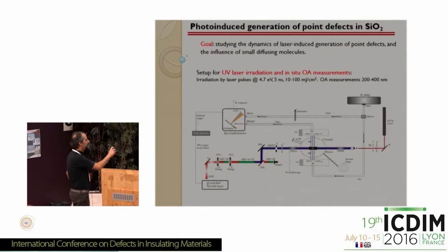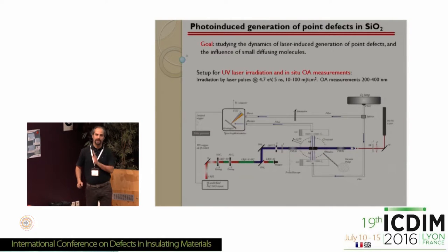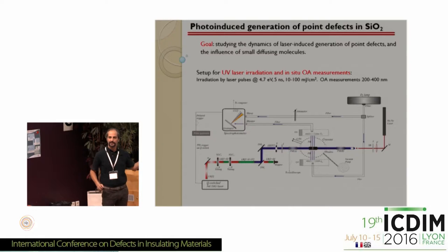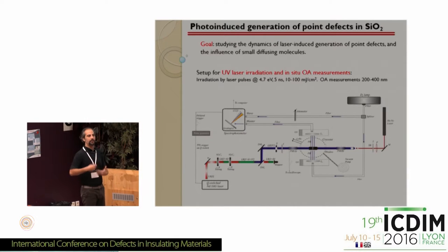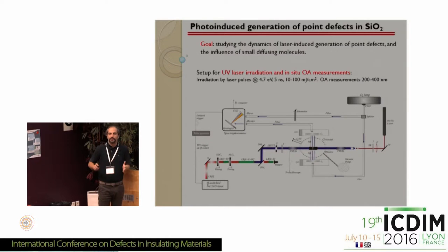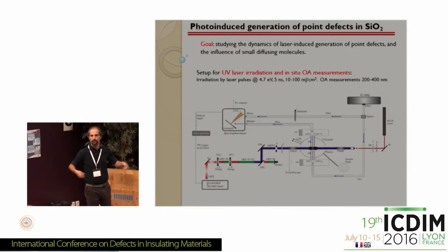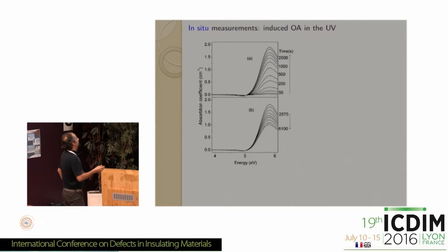In this setup, the sample, which is here, is being exposed to high-power ultraviolet radiation, which is capable of generating point defects. And then, during this irradiation, we continuously monitor the absorption spectrum of the sample by an optical fiber spectrophotometer. And these measurements continue even after the laser is turned off, because, as I will show you, there are kinetics that occur immediately after the end of the irradiation that you would have missed completely with an ex situ approach, okay? So this is an example of a result that you can get with this experiment.